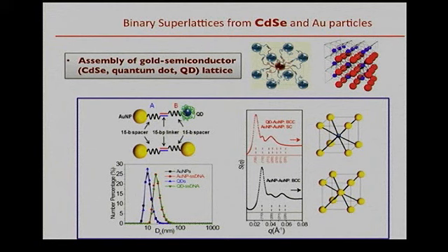This polymer shell has two functions. First of all, it allows us to do the chemistry not on the surface of the quantum dot, but on a polymer shell, which completely preserves the optical properties of those quantum dots. Second, we can match the size so that the quantum dot with the shell has exactly the same size as the gold particle which we use in a control experiment. As you can see here, you cannot distinguish. So basically, we're truly substituting the gold particle with this quantum dot.